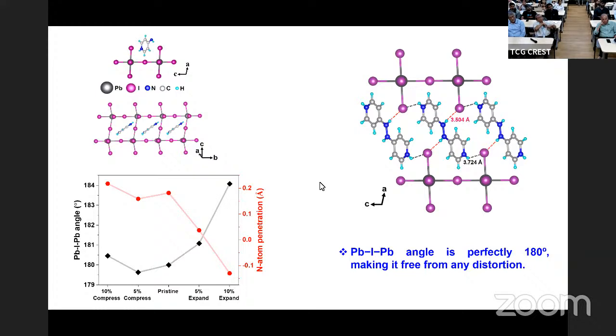So it doesn't magnetically order. So I have a paramagnetic system. Down to 2 Kelvin, we can see. And if I extrapolate the Curie-Weiss temperature, which gives me an idea about the interaction, it is also very close to 0, simply because the chlorine-chlorine distance is much larger. And I told you the bromine-bromine distance is surprisingly small. And the bromine compound has an antiferromagnetic transition on the order of 7 Kelvin or so, very low. But the bromine compound is not ferroelectric, whereas the chloride compound is ferroelectric. I didn't tell you that story. And that's a paper we are writing right now.